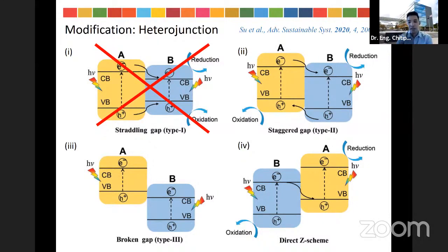And type 4 is similar to type 2, but the electron transfer is different. The excited electron moves from the conduction band of material B to the valence band top of material A. So the hole does not move to accumulate in the valence band top of material B. So this type also avoids the recombination because we can keep the important electron in the conduction band of material A and the hole in the valence band of material B. So we call this one a Z-scheme heterojunction.